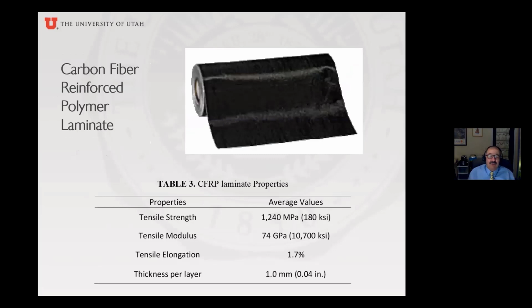And the carbon fiber reinforced polymer laminates, this is the sheets. Tensile strength is still good. It's unidirectional fiber in this direction that you see my cursor going up and down. It has very high tensile strength, 180 ksi. Tensile modulus is pretty low, 10,700. But the biggest problem is tensile elongation, 1.7%. And the thickness is very thin, 0.04 inches. But it does very well in confinement.